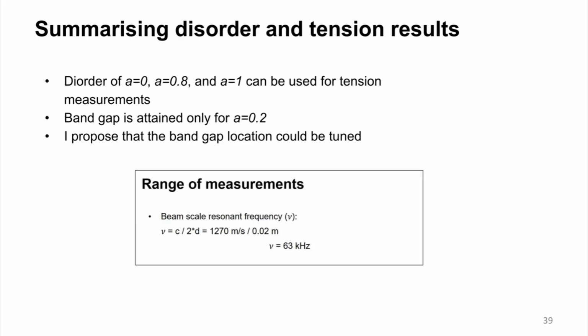gap appears. There are also other material properties on which it depends, which dictate the velocity of sound in the metamaterial, but it does remain that disorder is what caused the band gap in the first place, and the interpoint spacing is one of the parameters we could change to change the location of the band gap that appears after perturbation of the original ordered point cloud.